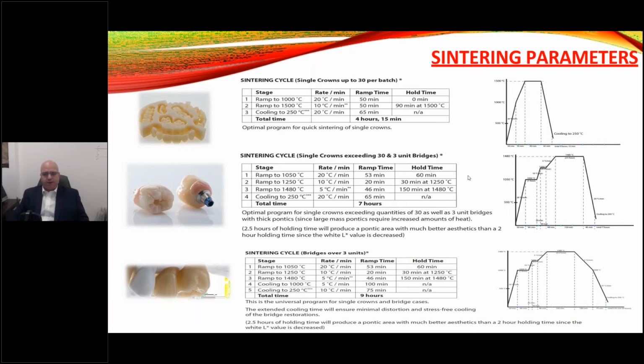and again, it all has to do with mass, there is a 7-hour sintering cycle. You can see it's actually 3 stages of going up to 1050, and then another raise of heat to 1250, and then finally 1480, which is a lower temperature than the 1500, rather. You can see it incrementally goes up to where the transitions really sinter well, at a lower temperature of 1480 rather than the 1500. It does take 7 hours, but you can batch in a greater way.